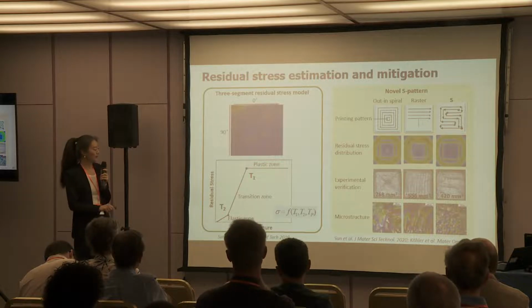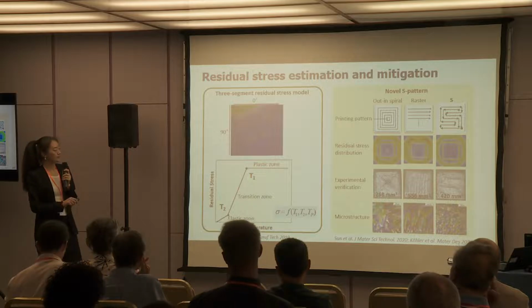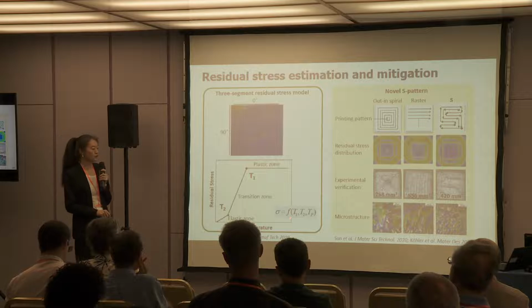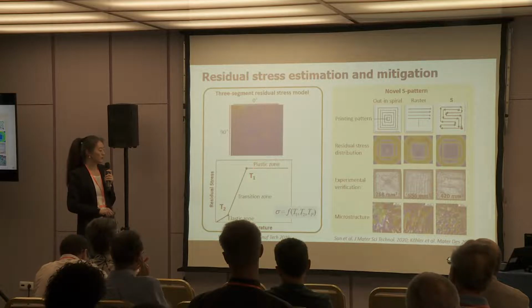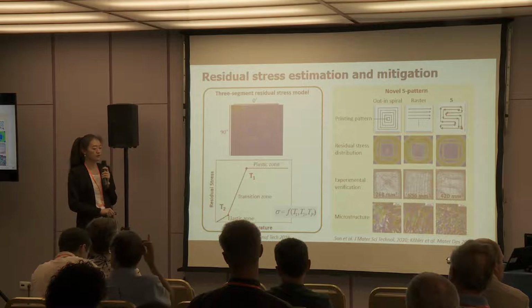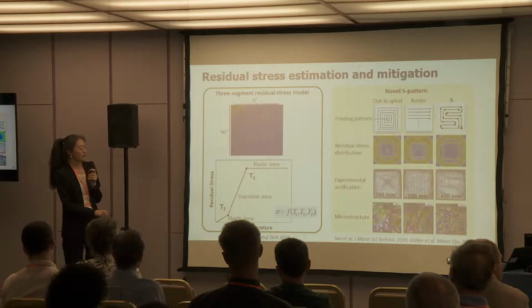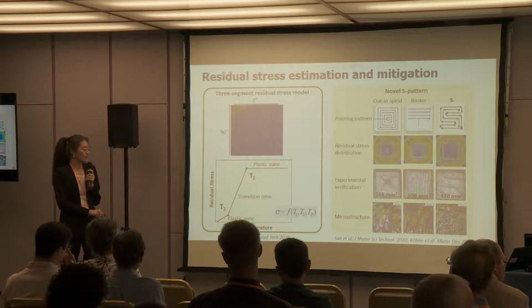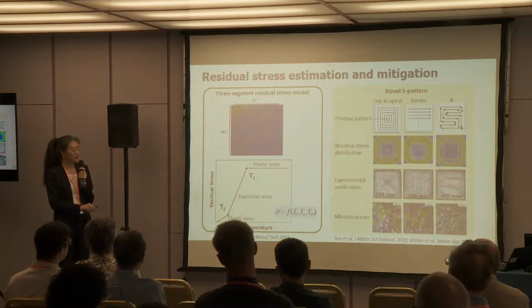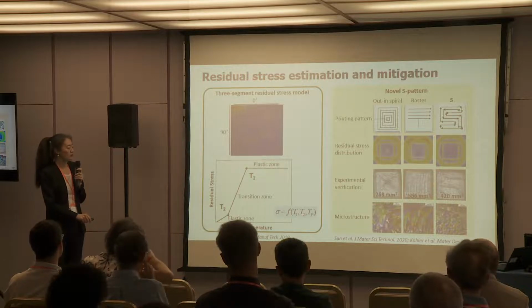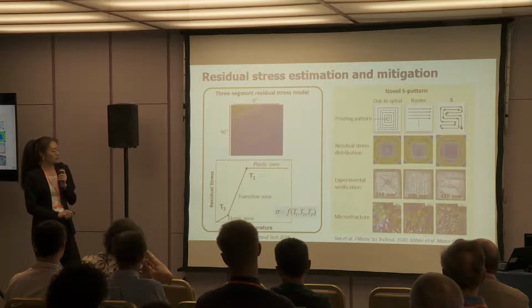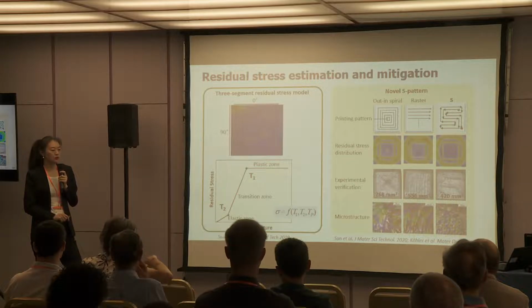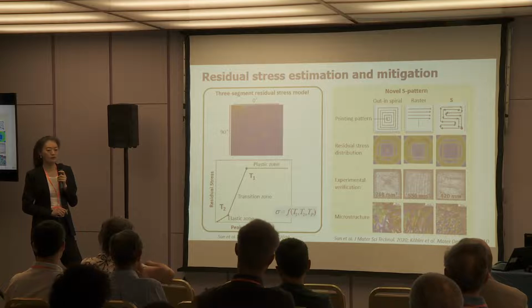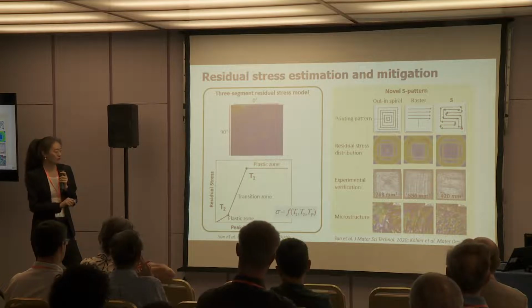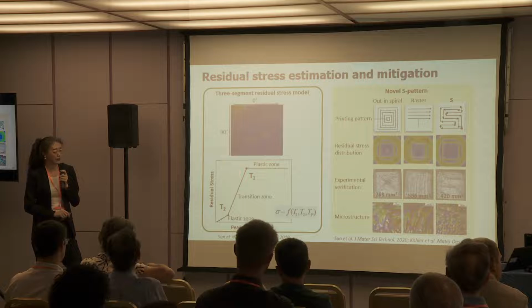And the model looks like here. The advantage of this model is that we directly link the residual stress to 3 temperature parameters. Here T1 and T2 relate to the transition of the mechanical properties at different regions, and TP is the peak temperature. By correlating these 3 temperature parameters, using the model we are able to link the residual stress to only the heat input during the AM process. So it saves a lot of effort to predict the residual stress using this model.